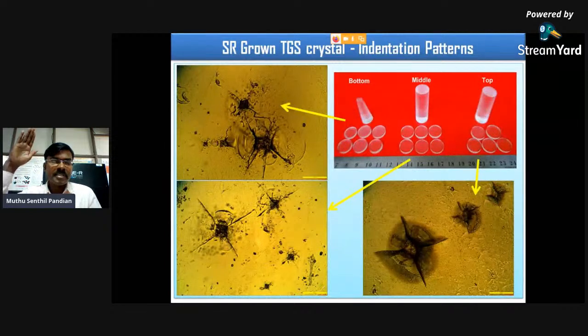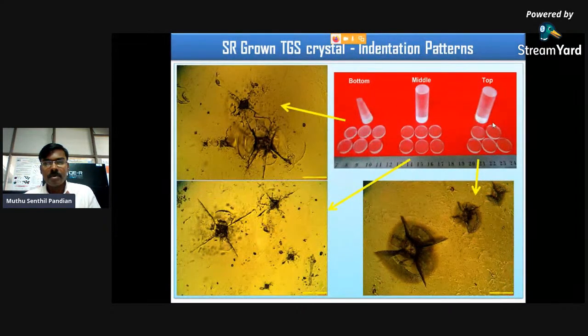This is the 15 centimeter longest TGS crystal. This is the bottom portion. This is the middle portion. This is the top portion. We have carried out the Vickers microhardness measurement for this bottom, middle, and top portion. The number of micro cracks appearing in the indentation is high in the SR method. For that purpose only, we have carried out this Vickers microhardness measurement. We have checked the hardness property of the grown crystal.